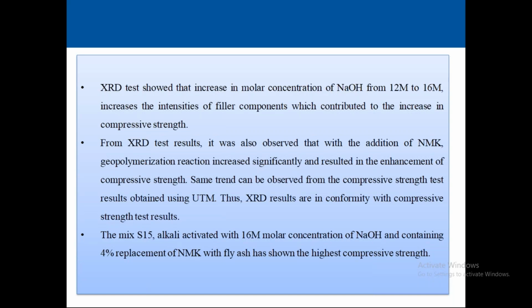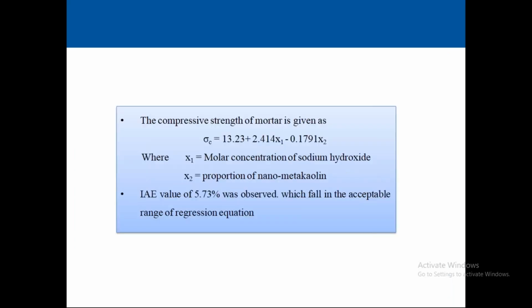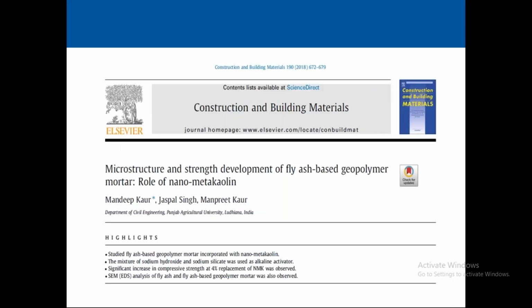From XRD test results, it was also observed that with the addition of NMK, geopolymerization reaction increased significantly and resulted in the enhancement of compressive strength. The same trend can be observed from compressive strength results using the machine. So XRD test results are in conformity with compressive strength results. So this is the compressive strength relation, and from this we could publish two papers in one of the important journals, Construction and Building Materials, because this nano metakaolin and geopolymerization mortar process is something which is latest.